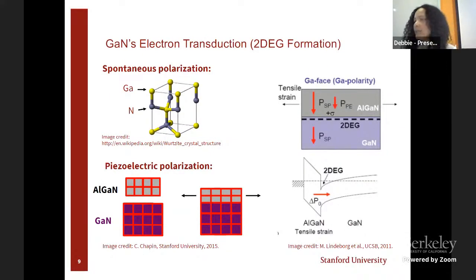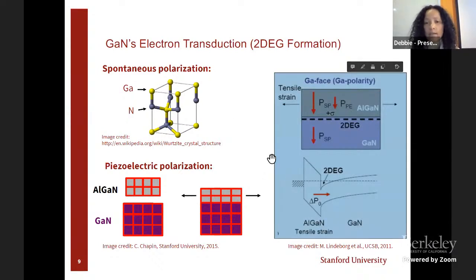I also want to tell you a little bit about why gallium nitride is different in comparison to your traditional silicon CMOS technology. In silicon CMOS, you're usually relying on doped junctions to create your transistor or your transducer. Whereas in gallium nitride, the transduction is a little bit different for the heterostructured class of gallium nitride-based electronics. Something we leverage here for transduction is the two-dimensional electron gas. This is, again, different from a doped junction, and this two-dimensional electron gas is a highly conductive sheet of electrons at the interface of a heterostructure.